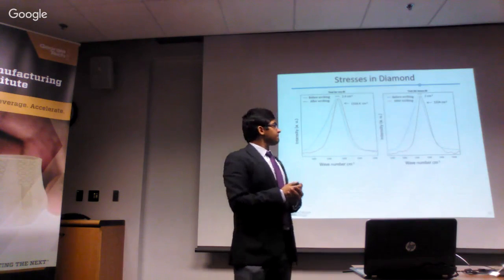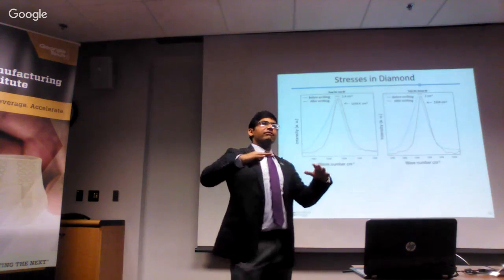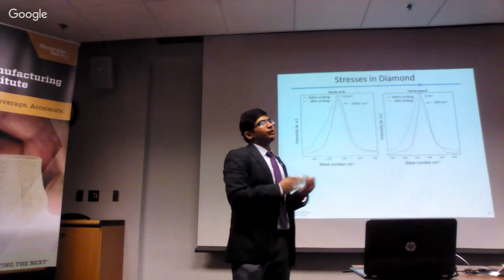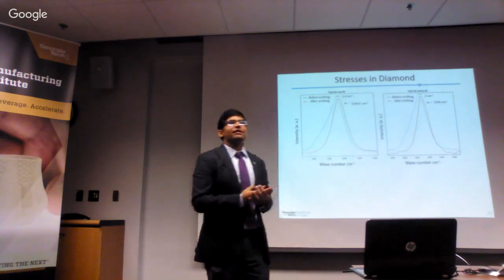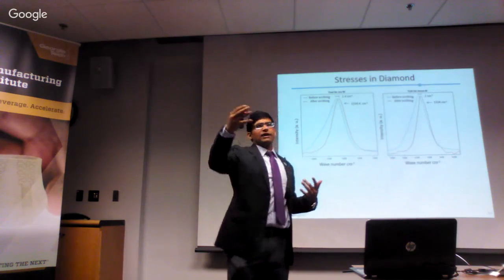If diamond goes into graphite, there is a lot more difference in the full width at half maximum. But we are not seeing graphite here. The change in the peak shift is only 2 cm^-1, whereas graphite is 1334 to more like 1350, which is one of the graphite peaks.